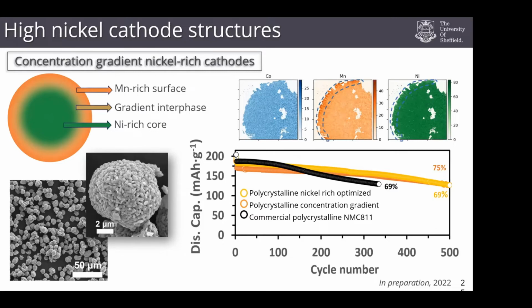And so we try to avoid that by tuning the chemistry so that we very gradually introduce manganese onto the surface. That's what this picture is trying to show you. That darker orange is gradually coming into the surface of those particles. And what we see is this black line is telling you the capacity, which is the amount of charge under certain conditions that your battery is storing over many hundreds of cycles. This is commercial materials, and so you lose capacity over time. And these are our concentration gradient materials. They retain capacity for much, much longer than commercial materials do.